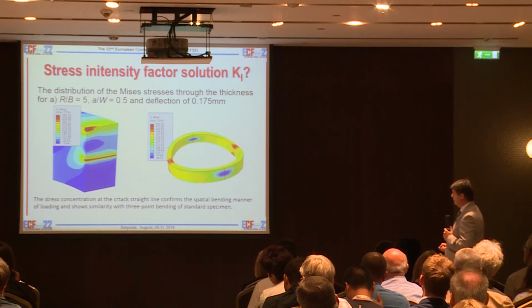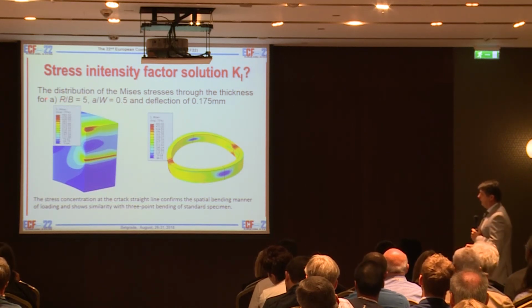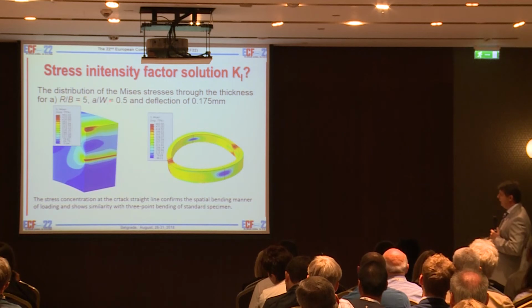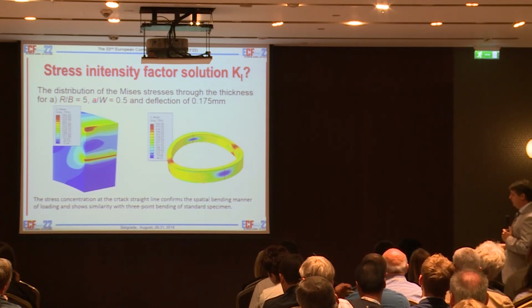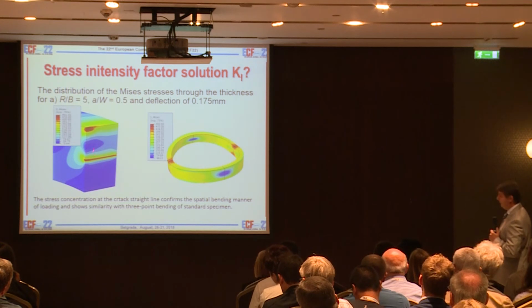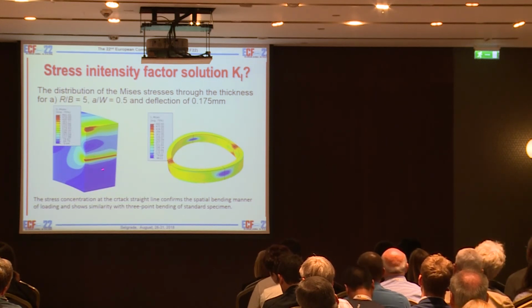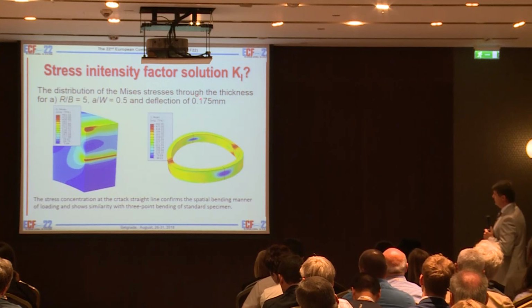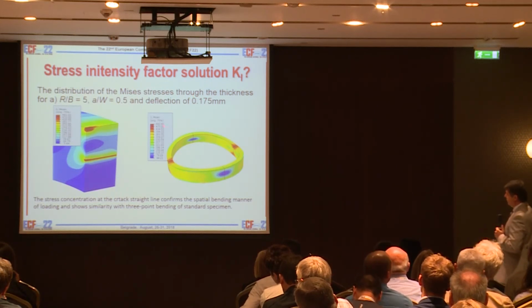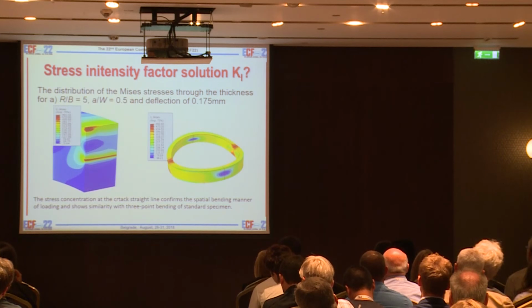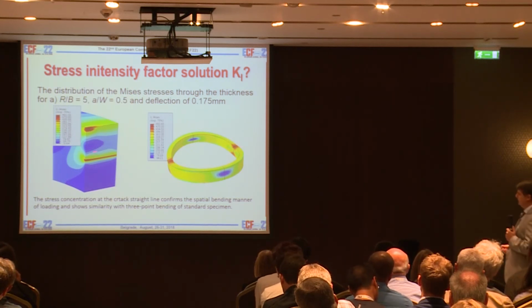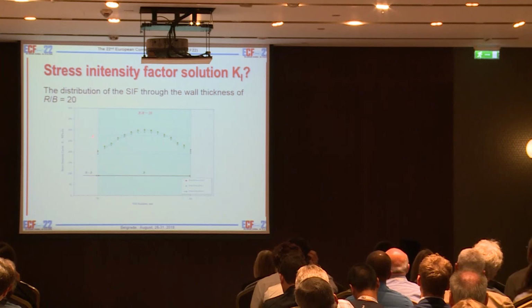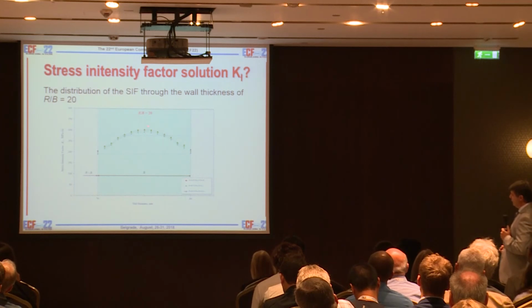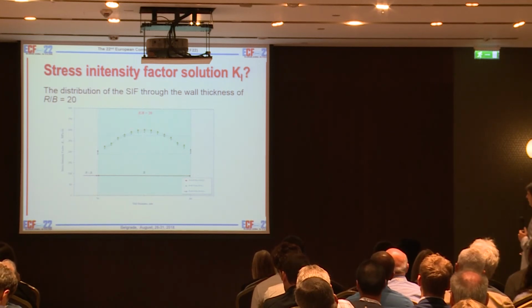So here we have an example with the ratio R over B of 5 with the crack notch, actually notch 0.5 of width, so crack ratio, and we put here a deflection of 0.175 millimeters. You can see for this model what is the stress that we got on the surface, and also what is the outside stress and what is in this section. So also in this case, of course, we got a quite symmetric distribution of stress intensity factor. Of course, the highest value is in the middle. So here is the outside, and here is the inside area.